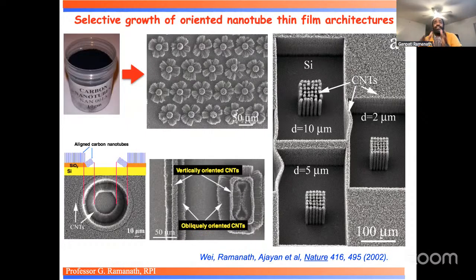Now, here is one of the first things that I did when I came to RPI. And you can see this can actually win. In fact, this has won many art and science kind of competitions. It has won many prizes. What you're seeing here is a flowery architecture and oriented architecture of bunches of carbon nanotubes. Now, carbon nanotube is like a black little powder that is shown on the left side top. And when my colleague came and said, oh, this would be good to use in microelectronics, I said, not in a million years, unless you do something to orient it in a highly precise way, in a way that you want to orient it. And we figured out a way of chemical vapor deposition, which is completely a bulk process, but the selectivity on silica as opposed to silicon gives you this orientation. You can make these brilliant architectures.